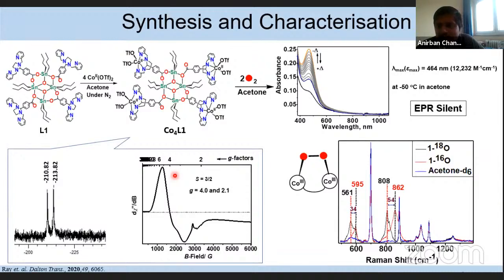Yeah, that reaction we did, as it was one question from the reviewer, and we didn't see any kind of change in the presence of proton. First we take the cobalt solution, then add proton, triflic acid or perchloric acid, and then add oxygen, and we found an equal amount of formation of the product. That was at low temperature, because at room temperature there is always self decay involved. From there we concluded that the proton is not making any difference to the formation of this peroxo species.